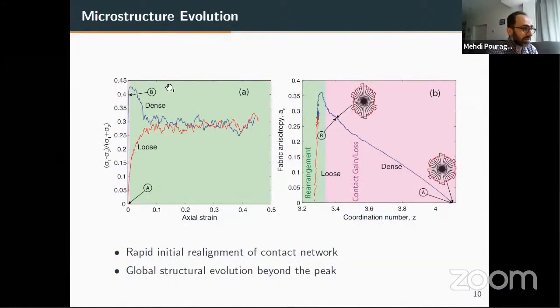Okay, if you go back to this picture, and this is a picture that I'm going to refer to a lot in this talk. Now we see that if you look at the dense sample, we have initially this large range where essentially the contact structure, the contact network, is evolving due to contact gain and loss. It's very rapid. No strain, you can barely see that purple zone in the left-hand side. And it gets to a limit where it starts showing the global deformation, and after it reaches the peak, it starts to show large deformations, which is due to contact rearrangement due to sliding.